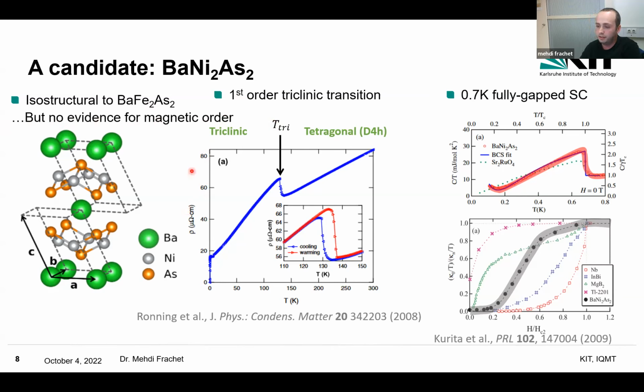If you look at the resistance as a function of temperature, you see close to 135 Kelvin this strong first-order transition, which signals a change in the crystal structure. The low temperature crystal structure is triclinic, which is the lowest symmetry you can get from tetragonal. It's also a superconductor, at quite low temperature, 0.6, 0.7 Kelvin, and you see this nice specific heat and thermal conductivity data. There is no residual thermal conductivity at low temperature, so it's a fully gapped superconductor.